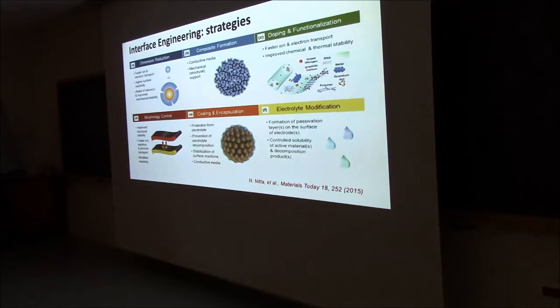Now, there are all kinds of strategies in which people try to control this interface engineering. You go from particles to smaller length scales, so you have more surface area compared to the bulk, so you have much more connection there. Make composites of different materials, dope it with different elements to improve this. Change the surface morphology, coating of specific layers, very often oxides, to limit all kinds of negative processes, so that won't happen. But also maybe add something to the liquids to stabilize this much more. So that's something which is happening and which they can put into, let's say, the current technologies. You don't have to wait for this solid state.